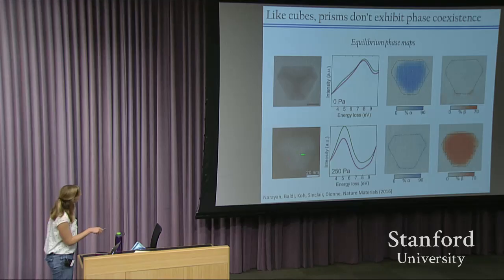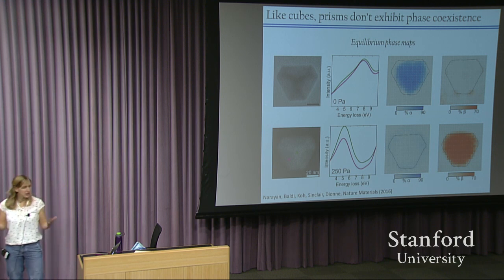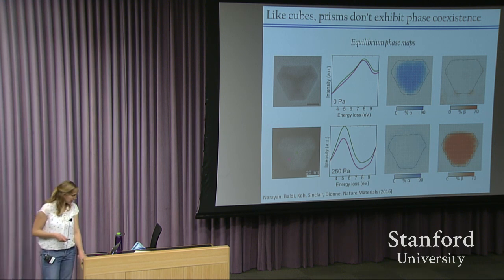So first, let's take a look at the prisms. Let's do an EELS map and just confirm that we don't have phase coexistence. Here's the EELS map for a prism, and again, just like with the cubes, these prisms exist either only in the alpha phase or in the beta phase. In thermodynamic equilibrium, there isn't coexistence.